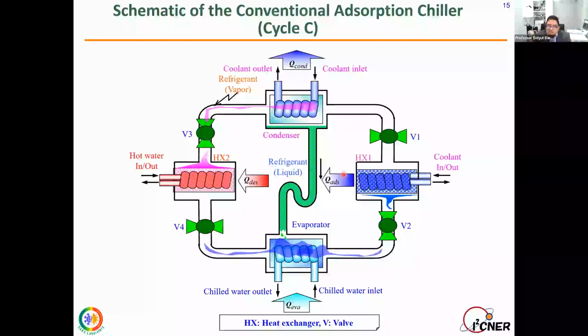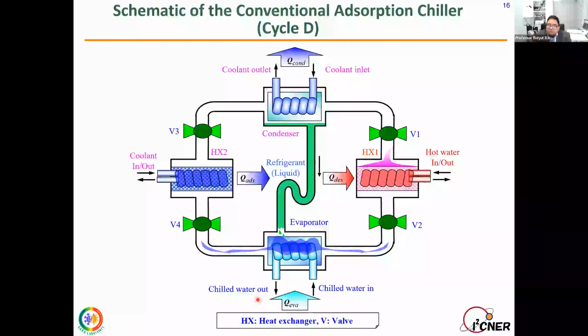And here you can see this is the opposite of cycle A. Now this is our desorption bed, and moisture goes from this bed to the condenser, and water vapor from the evaporator goes to our adsorber bed via valve 2. So this is the opposite of our cycle A, and we can continuously get our cooling energy from this evaporator. This is the way we are doing it. Then again we have to close all 4 valves and pre-cool this one and preheat this heat exchanger so that it can go to the next stage. So continuously it can work with heating and cooling.